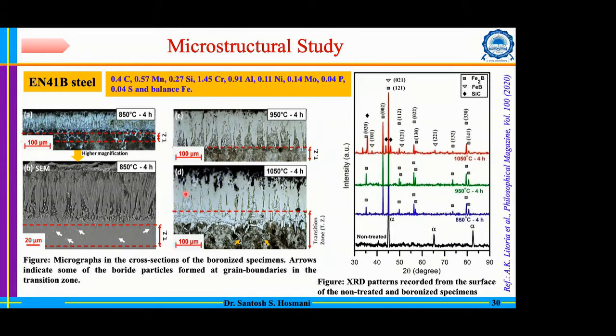And you can also see, surrounding the boride, some kind of different contrast, which appears different than the matrix. Why is that contrast there? That is because of the different chemistry of that region, and we call this region the transition zone. So we have used the terms boride columns, matrix, transition zone region, and then the core region. These are the terminologies we have used in this case.